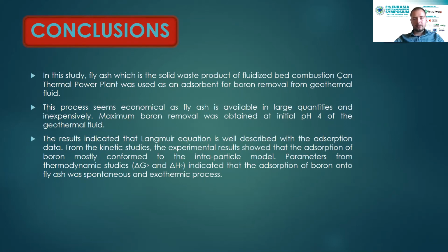Maximum boron removal was obtained at initial pH 4 of the geothermal fluids. The results indicated that the Langmuir equation well describes the adsorption data. From the kinetic studies, the experimental results show that the adsorption of boron mostly conformed to the intraparticle model. Parameters from thermodynamic studies indicated that the adsorption of boron on the fly ash was a spontaneous and exothermic process.